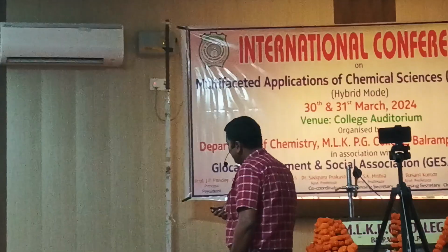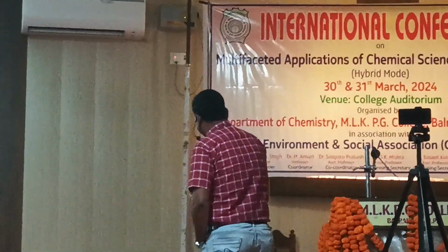nanomaterials, which have a size of 11 nanometer and a carbon and oxygen elemental composition, with carboxylic acid functional groups on the surface. We characterized these using HRTEM and XPS study.